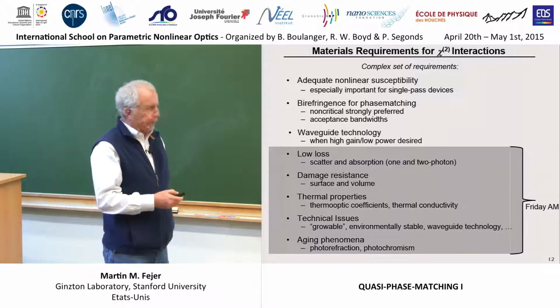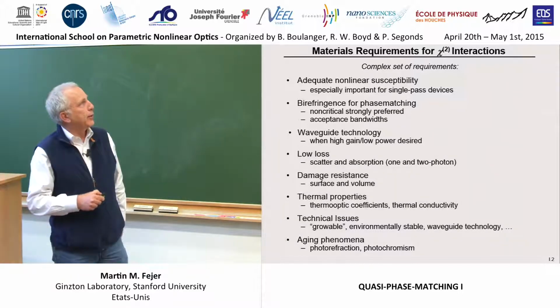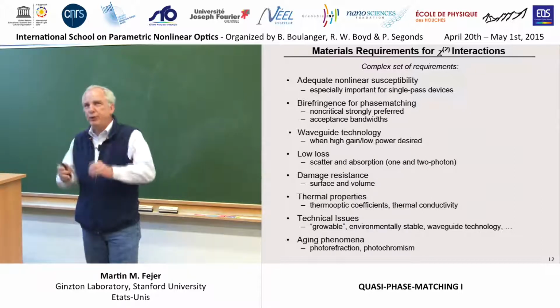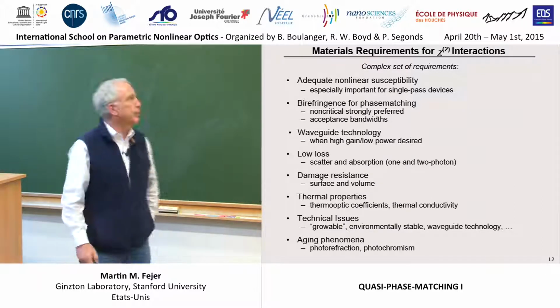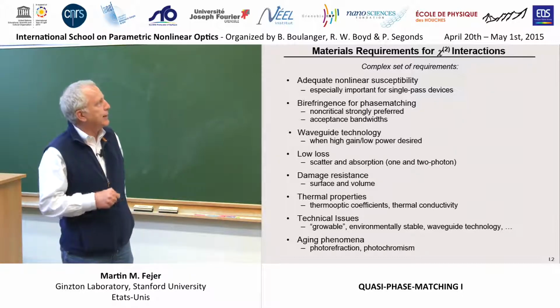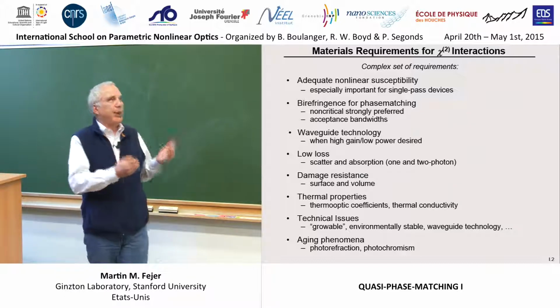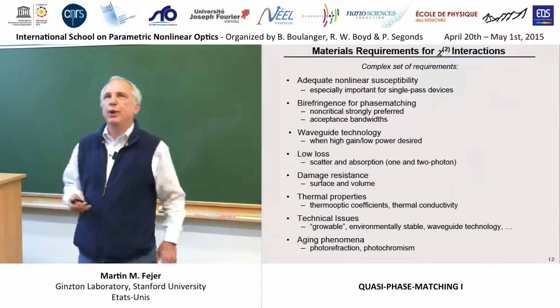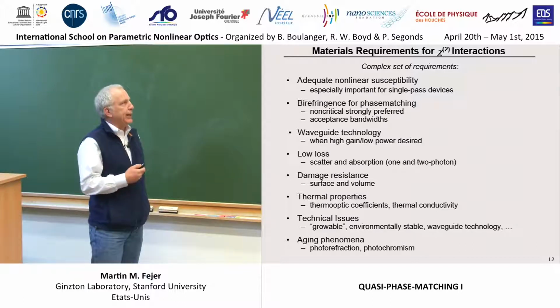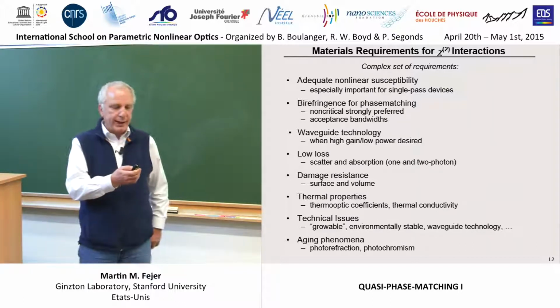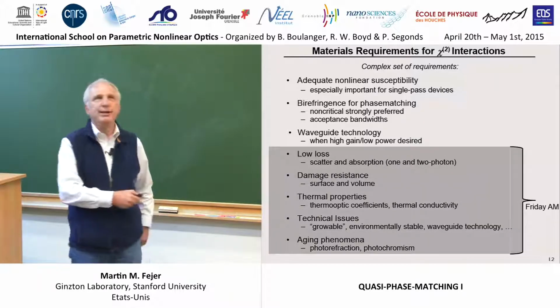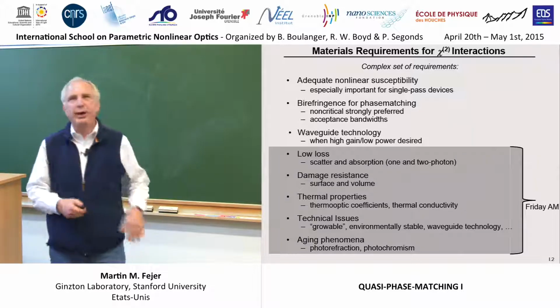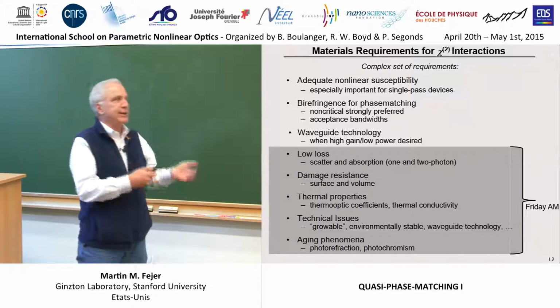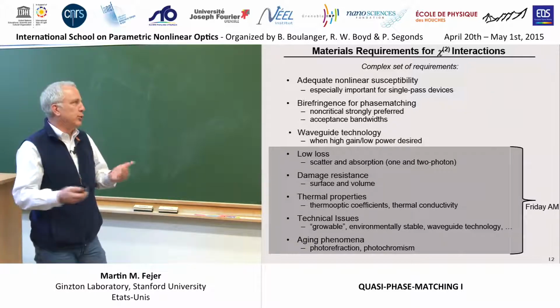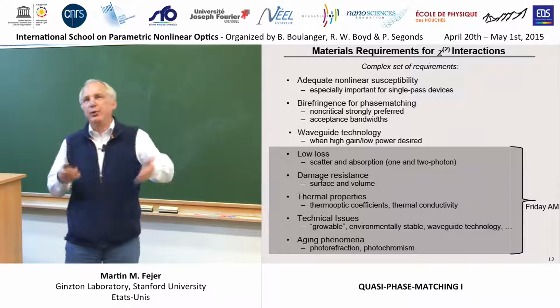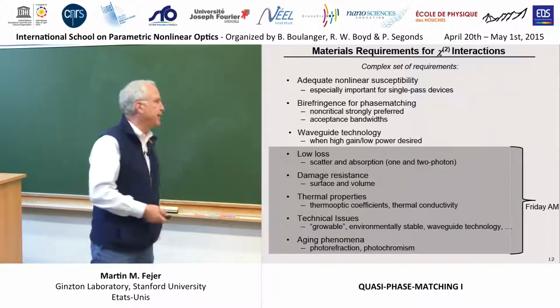As we've heard from several of the speakers today and yesterday, there are a rather complex set of requirements that a useful material for quadratic nonlinear optics has to meet. Some intrinsic properties like having adequate nonlinear susceptibility, birefringence for phase matching, in many cases a waveguide technology if you want to operate at low powers or with high gains. And in addition to those, there's a whole set of extrinsic technical issues that are annoying but often determine whether a crystal is useful or not. Things like its optical absorption, its resistance to intensity damage, photo-induced aging mechanisms like photochromism and photorefraction, et cetera.